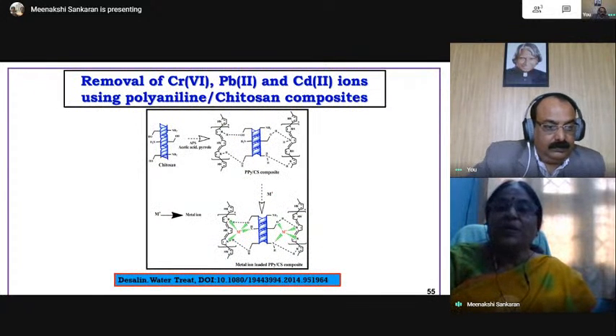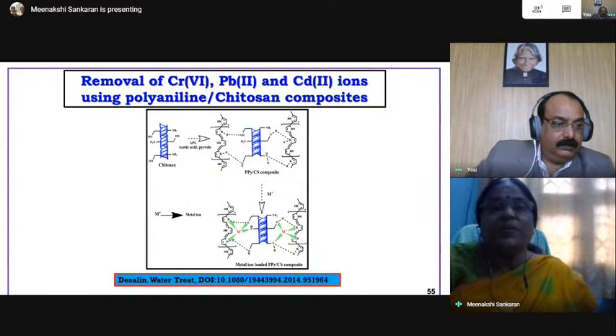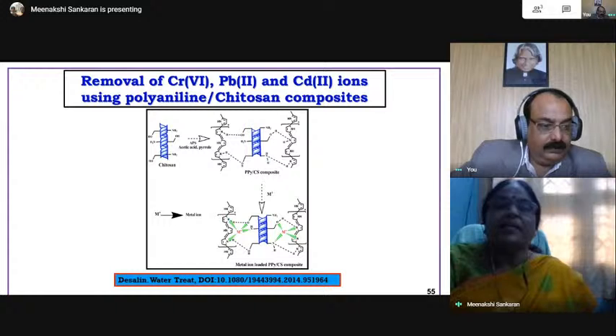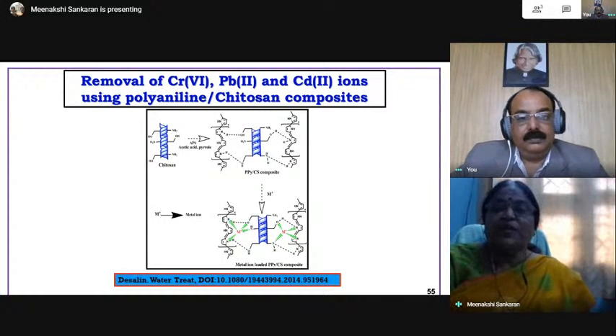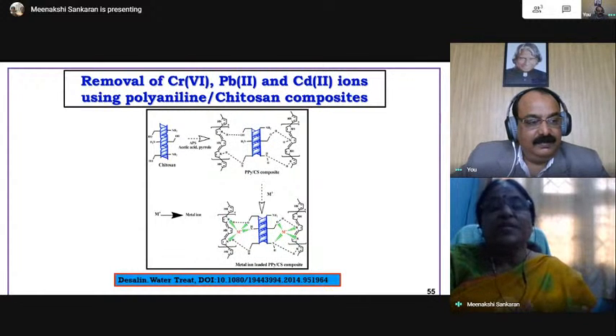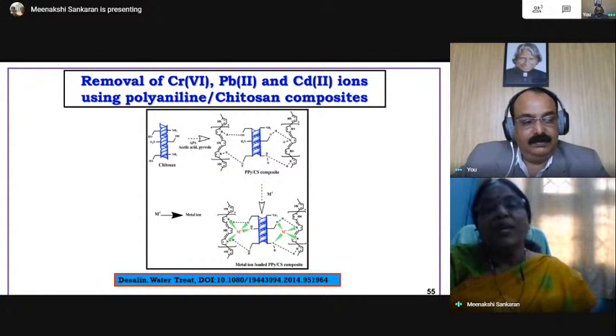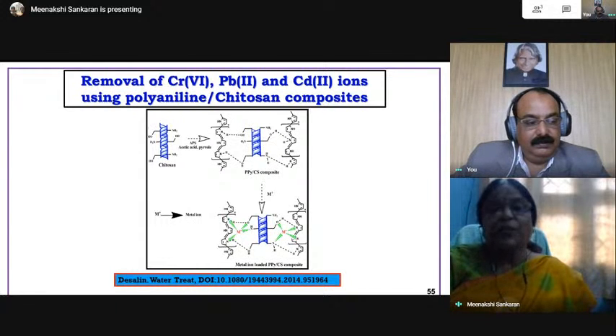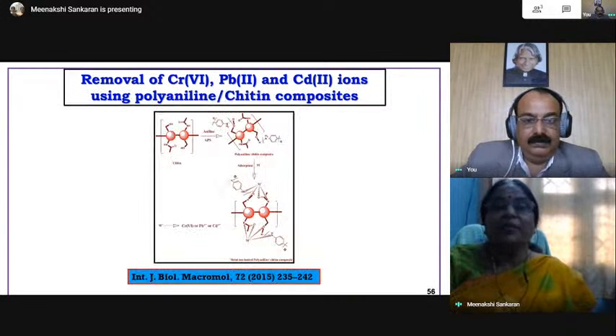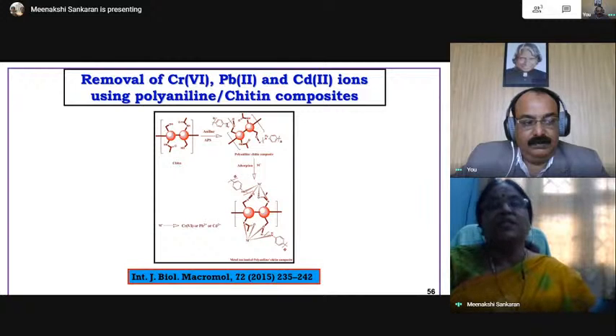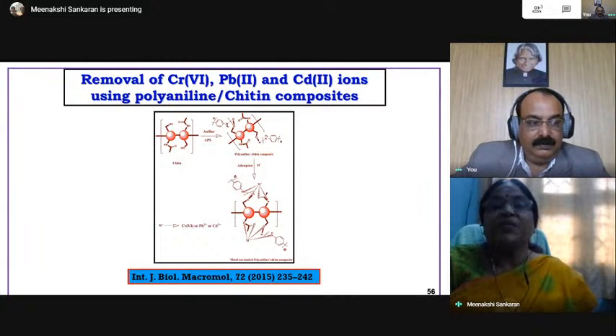And we have removed chromium, lead, and cadmium ions using polyaniline chitosan composites. I told you polyaniline is a conducting synthetic polymer, and chitosan is a biopolymer. We have mixed both, and this works due to a synergistic effect. Polyaniline has many amino groups, and chitosan also has many amino groups. Both combined together are able to remove more metal ions. Their strength and stability are also greater. So these materials we have prepared for the removal of chromate, lead, and cadmium. We have also made polyaniline chitin composites for the removal of chromium, lead, and cadmium. This material was also able to remove more of the heavy metals we selected.